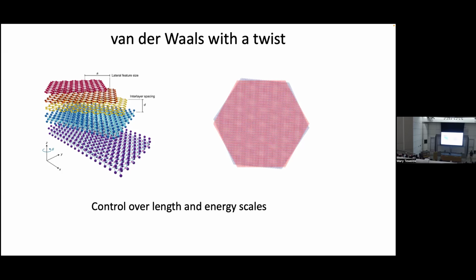They're just covalent. But for van der Waals materials in general, you can pick whichever interlayer twist you want. And what this does is it allows you to effectively introduce a new length scale into the problem, which is known as the moiré length. That is, you can see there's this interference pattern, this beating between the individual carbon lattices, that gives you something that's much, much larger than the carbon-carbon separation. And this, of course, also affects relevant low energy bands and so on and so forth.